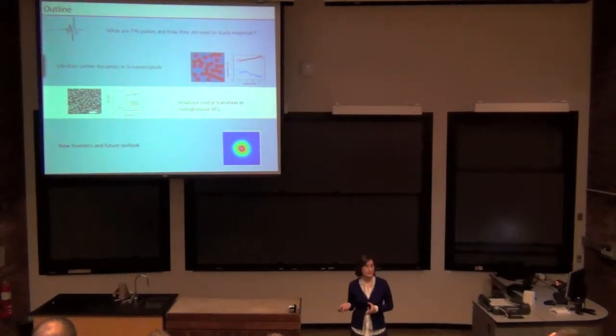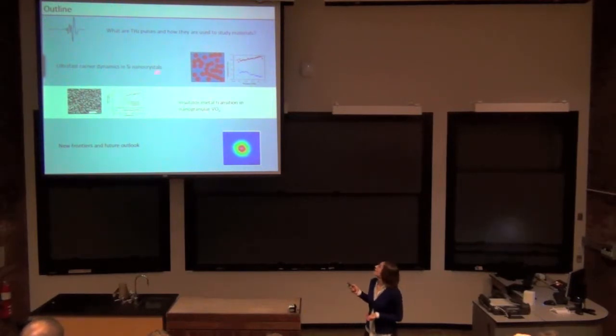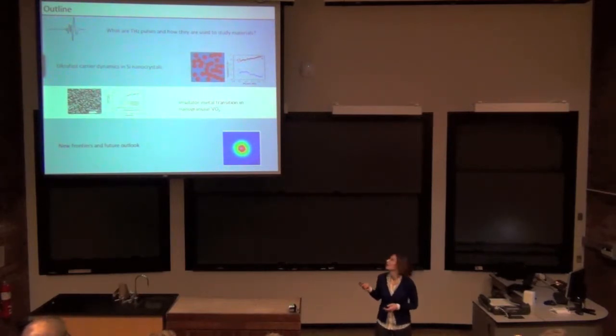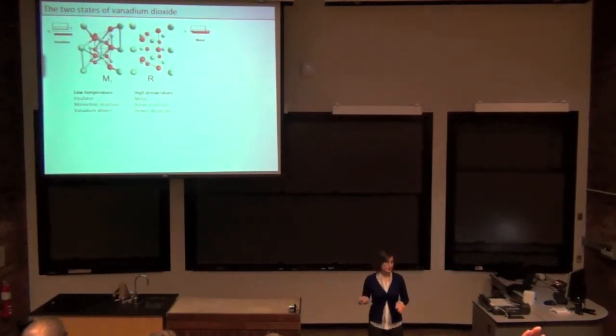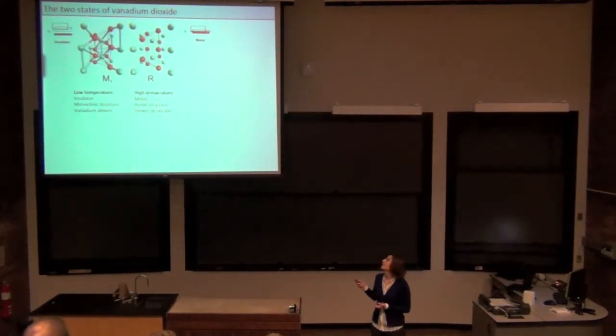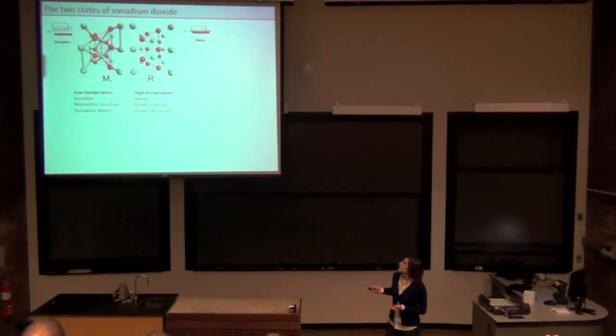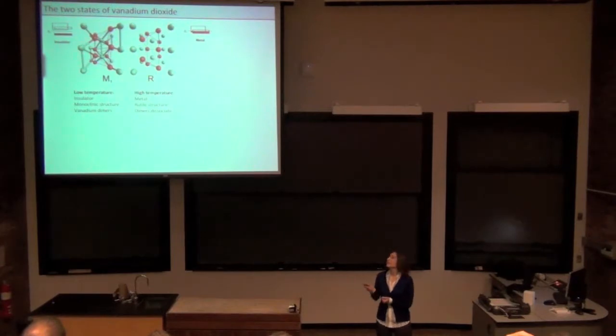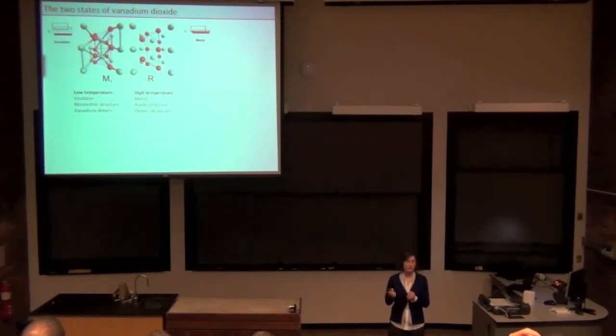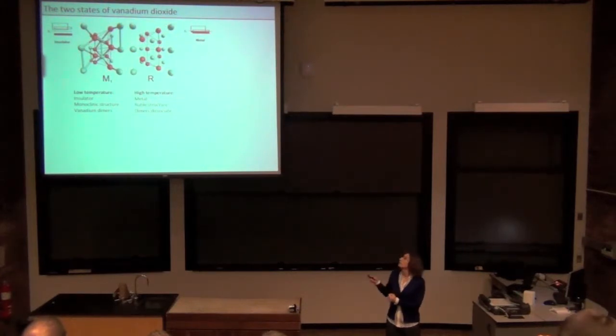a very different system where we applied a similar technique to study the conductivity. And that is the metal-insulator transition in VO2. It's nanogranular, but in this case, that actually turns out to not be important at all. So what's so interesting about vanadium dioxide? Well, at low temperatures, it's an insulator, and it has this monoclinic structure. And this monoclinic structure, green here, shows vanadium ions. They are dimerized. They form these dimers that are also tilted slightly from the C-axis, the vertical.